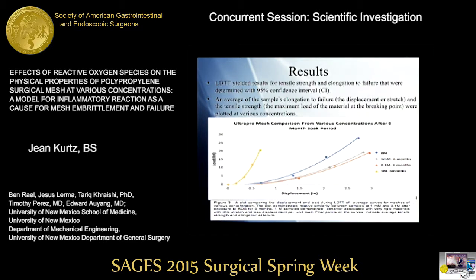What we found to be very interesting is if you'll look at the gray curve and the orange curve. The gray curve is our physiological concentration, that's the 1 millimolar, and the orange is the 0.1.